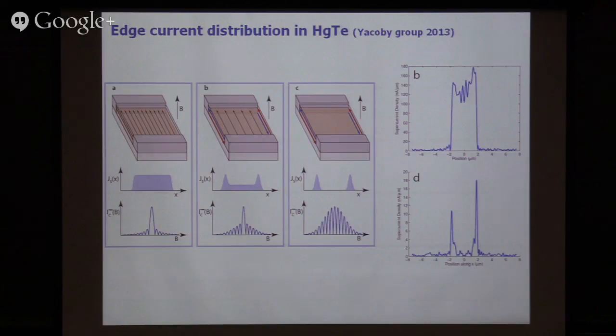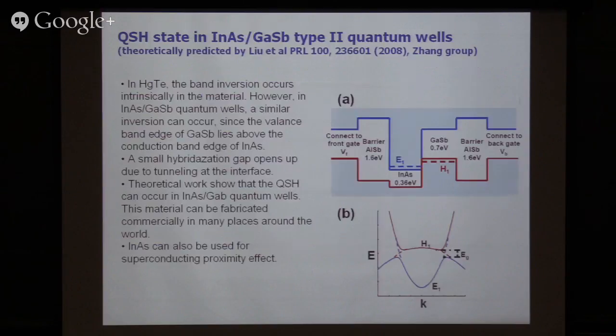But it turns out, by a very well accepted theory, that the Fourier transform of that spectrum, the Josephson current as a function of magnetic field, tells you about the spatial distribution of the current. And that spatial distribution, once you're tuned into the topological insulator state, as you see, is peaked on both edges. And if it's inside the conduction or valence band, the conduction goes everywhere. So from these patterns of supercurrent as a function of magnetic field, you can read off the spatial distribution of the current. In one case, it's localized on both edges. And in the other case, when the Fermi level is in the conduction or valence band, it goes everywhere. So this is a beautiful experimental design, which gives you such a striking real-space picture of edge state conduction.